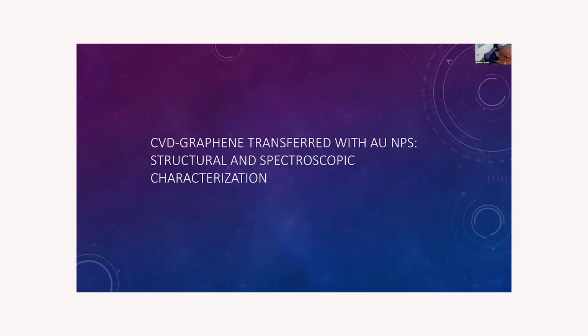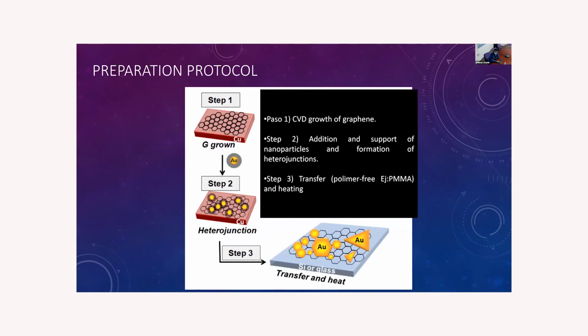And the other thing that I want to show you is a case using TERS, where we can analyze the system of gold nanoparticles on top of CVD graphene. In this case, the graphene was transferred onto a glass or silicon substrate, and using gold nanoparticles, we got a distribution of nanoparticles, in this case hexagonal and triangular ones, and also small nanoparticles.